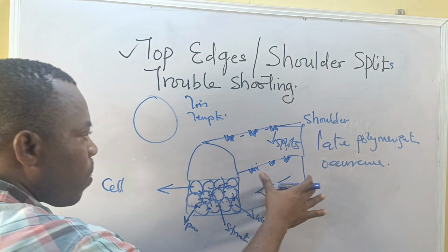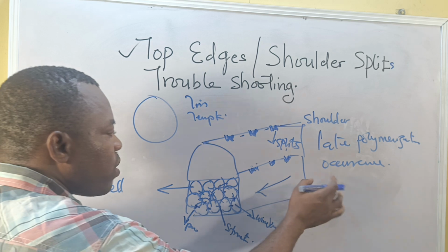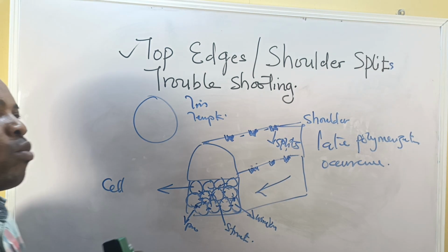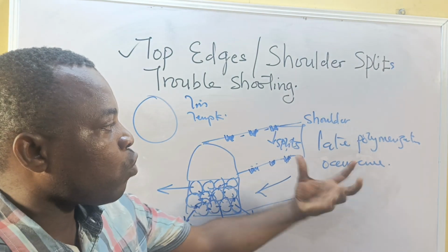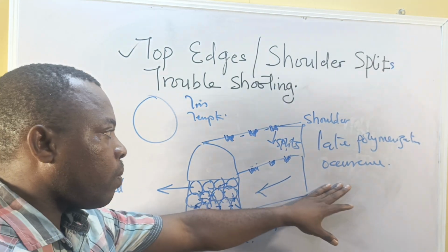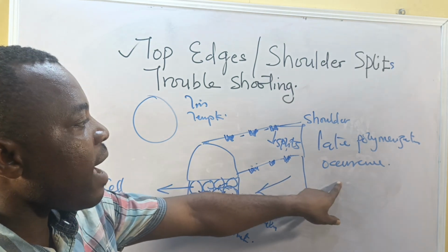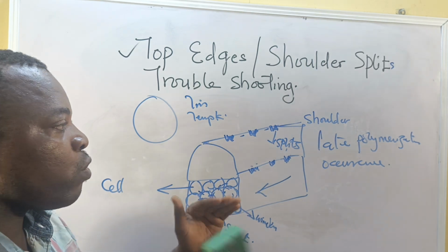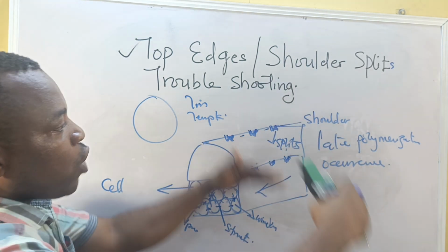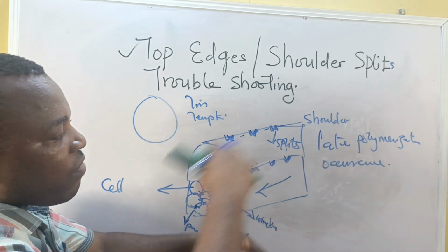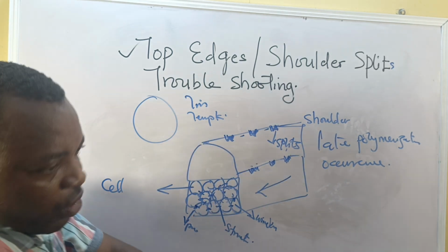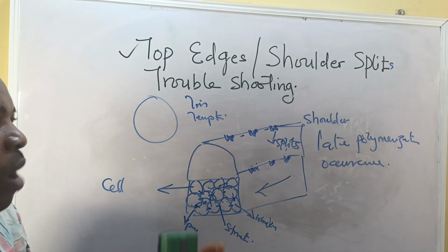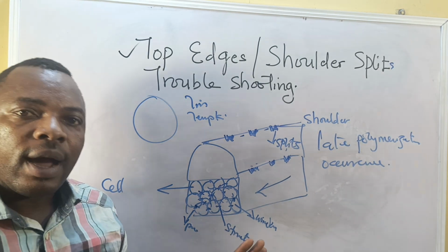But when it is too soon, what will happen is it will restrict the CO2 release. So the cell wall will suffer. It will try to release the CO2 under gas pressure, and if it could not, the internal gas pressure of the system falls below the atmospheric pressure. So in that case, the foam will shrink. So the two major effects also have a negative impact on the block: split and shrinkage. So in this case, you have to balance them in proportion through the temperature and regulation of your catalyst.